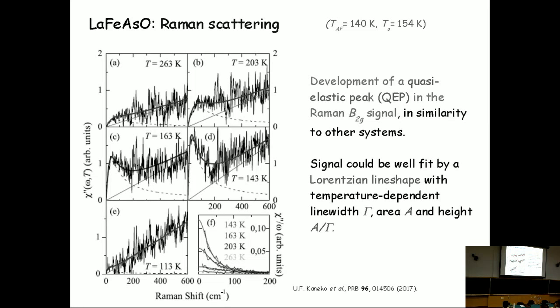This is the electronic Raman scattering spectrum for the 1111 sample, the undoped 1111. At high temperatures, you have basically noise. You may see something over here if you're optimistic. But when you cool down the material, the broad electronic Raman scattering starts to develop a specific structure, which can be deconvoluted as a sum of this dashed blue peak here,